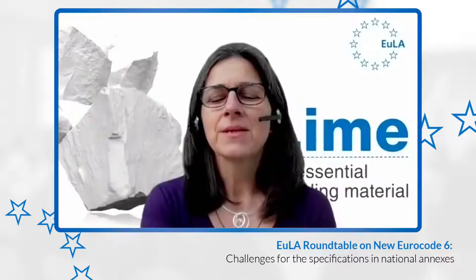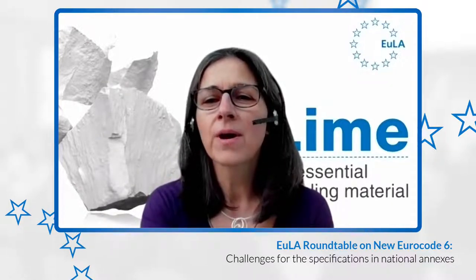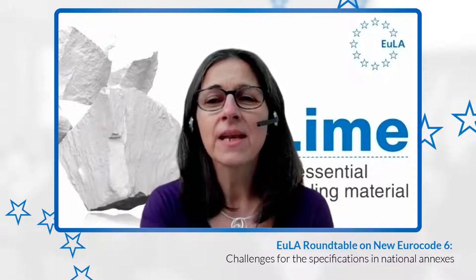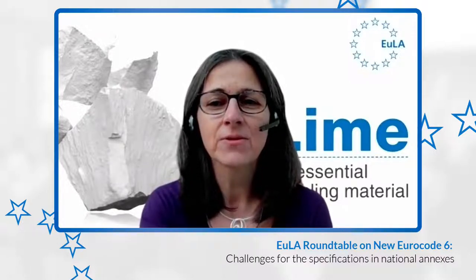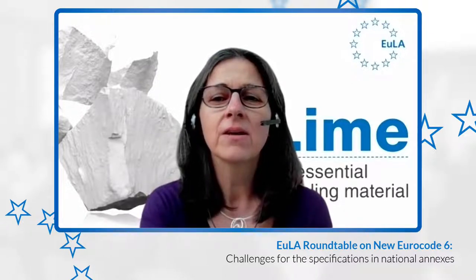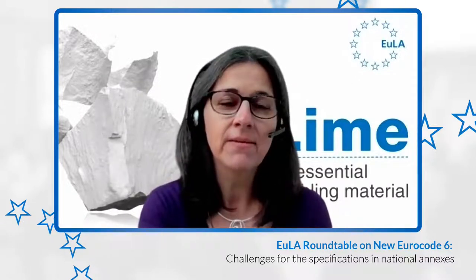And there are two questions on the creep testing. A first one from Paolo Lorenzo. Can you clarify the level of stress in the creep tests? What is constant for all mortars? And is there only one stress level? In the wall tests, they were constant at 2 N/mm².